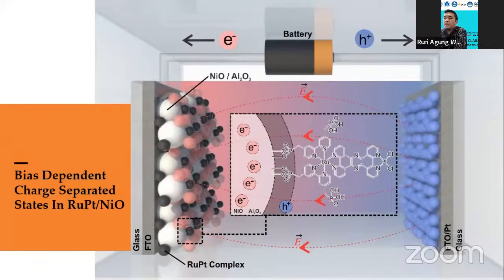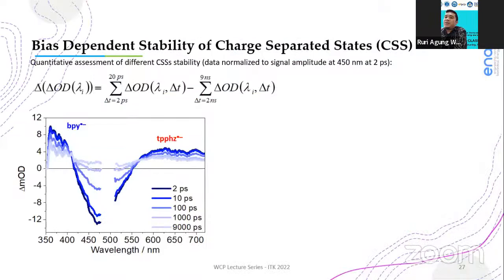So, as illustrated in this slide, we applied DC voltage bias, both positive and negative, to the dye-sensitized nickel oxide with and without passivation with aluminum oxide. So now we want to evaluate the transient absorption spectroscopy of this system. The transient absorption data of ruthenium platinum sensitized nickel oxide is shown here. Based on spectroelectrochemical data, we distinguish the bpy-based and TPPHZ-based charge separated states according to the signals at 380 nanometers and 650 nanometers.